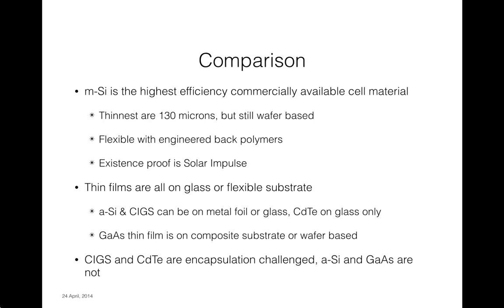Okay, so just to summarize the comparison, today the best commercially available material is clearly the monocrystalline silicon. The thinnest cells are about 130 microns. The existence proof of their use is the Solar Impulse aircraft, the Swiss effort, a manned aircraft. There's lots of public domain information on that airplane and how they do what they do. That cell has an engineered back polymer film which supports it for bending. So the cell's 130 microns, and then there's another polymer which is probably another 50 or 100 microns, which helps the cell stay intact during bending. And so the actual laminate is thicker than 130 microns.